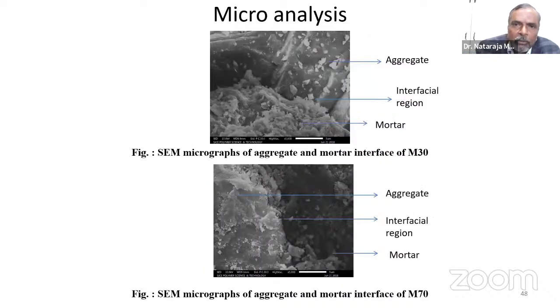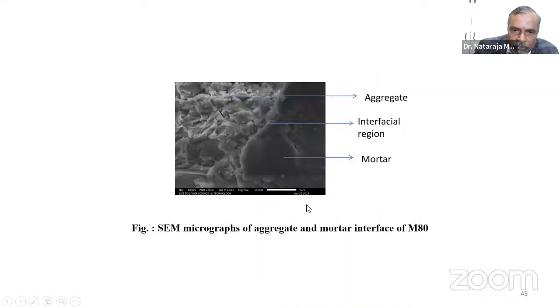And of course, we also have done the microanalysis. I'm really not aware whether many of you are familiar with this microanalysis. What I can tell you is, if you have an M30 concrete, this is the aggregate and this is the cement phase, and you can see some sort of a light distribution of this structure. There is, as if, a small gap at the micro level, at the nano level. But when you see M70 concrete, that gap is densified. And similarly, in the M80 concrete, the densification is becoming denser and denser at the micro level and the nano level.